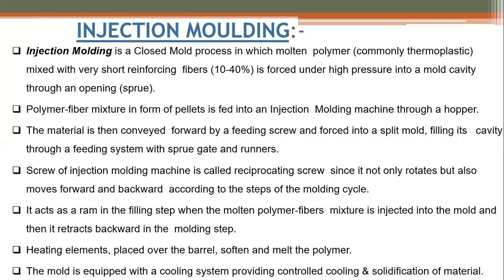The molten polymer is mixed with very short reinforcing fibers. The reinforcing fiber percentage is 10 to 40% only, and this is forced under high pressure into a mold cavity through an opening, that is a sprue. The sprue is the opening for the closed mold, and the reinforcement used is up to 10 to 40%.